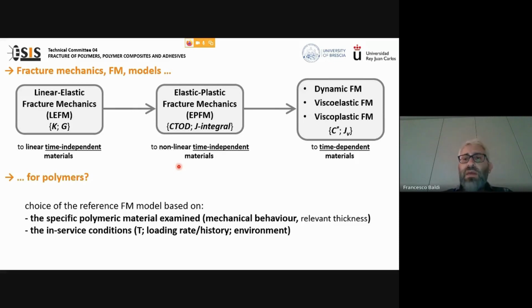More recently, fracture mechanics was extended also to viscoelastic and viscoplastic materials, and therefore to time-dependent materials. And in this case, we can count on the C-star integral parameter and viscoelastic J, and also it was possible to consider dynamic effects in this test. Now, this is, let's say, the tree of fracture mechanics.